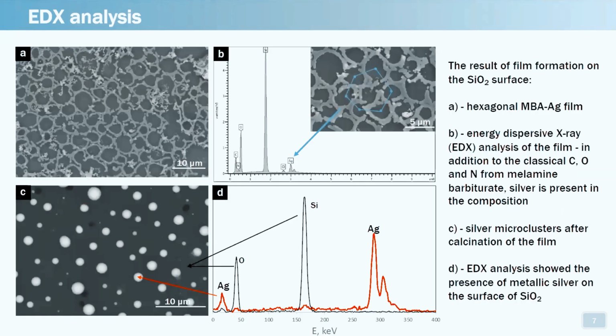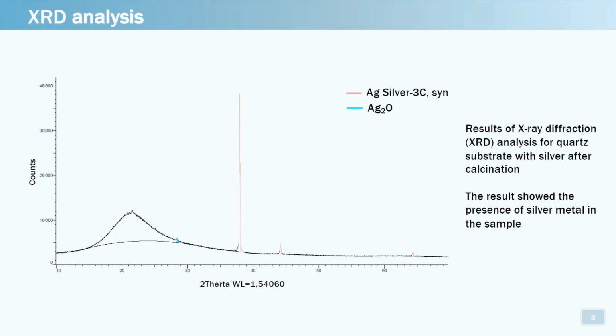At the next stage, it was important to identify the presence of silver in the samples. After the energy dispersive X-ray analysis, we understood that we've got argentum in the periodical hexagonal film, as well as in nanodots that we received after calcination. To check the accuracy of the results, the X-ray diffraction method was also performed. It showed the presence of metal silver in the sample and also small amounts of silver oxide.